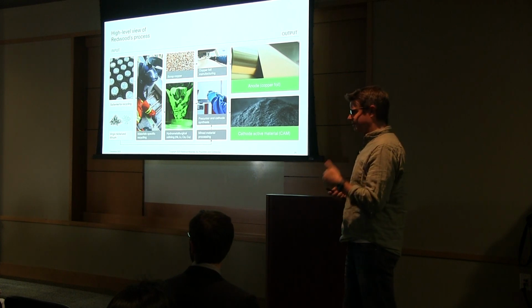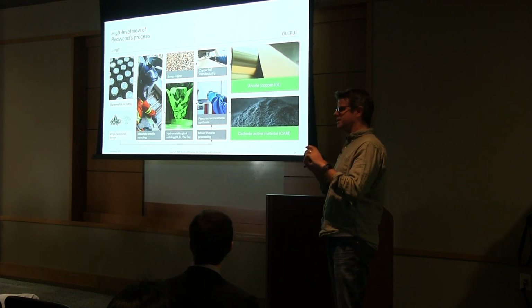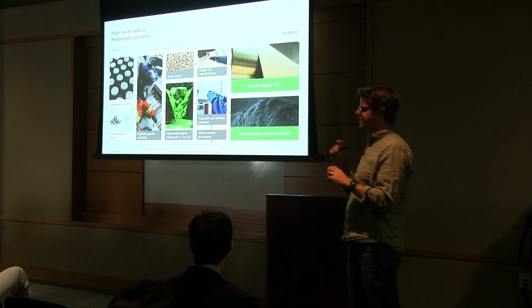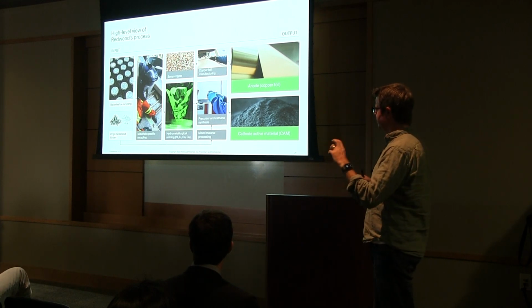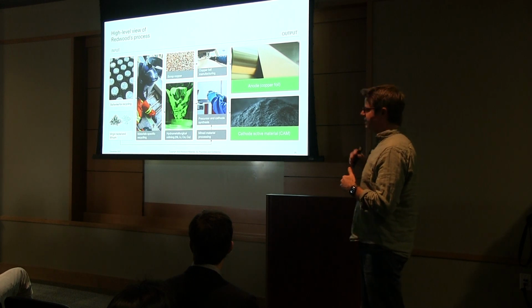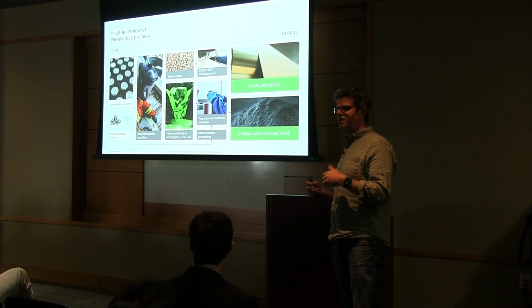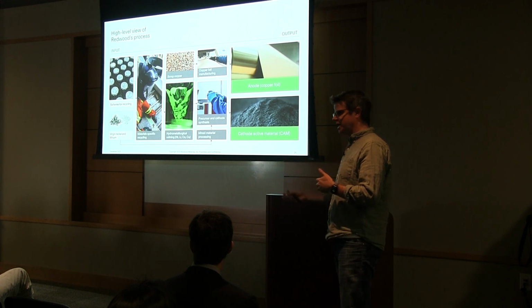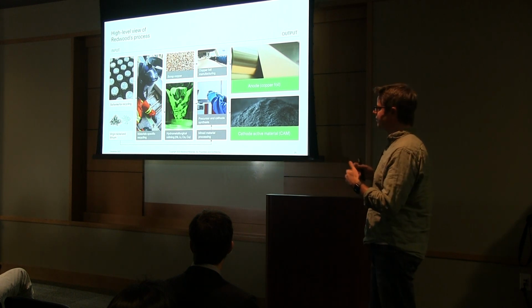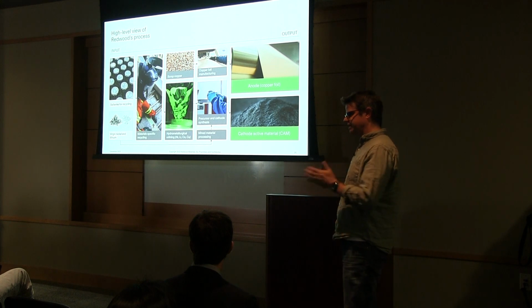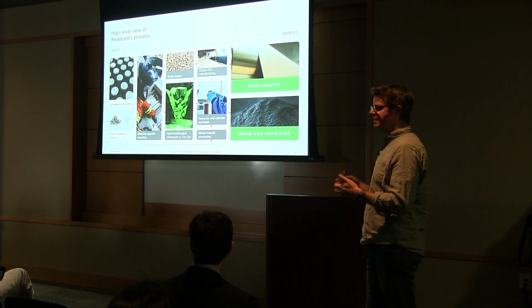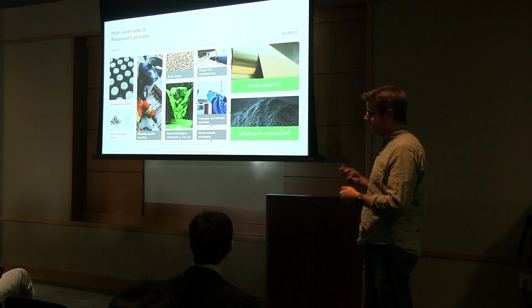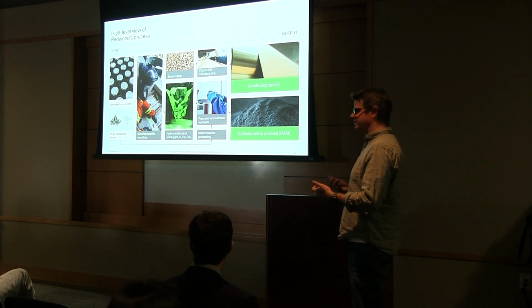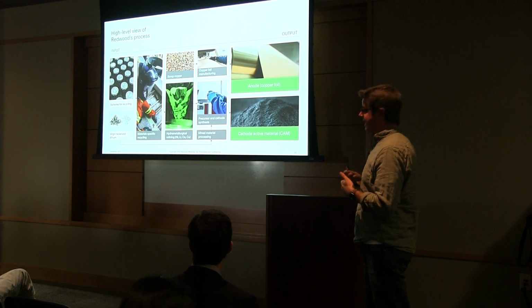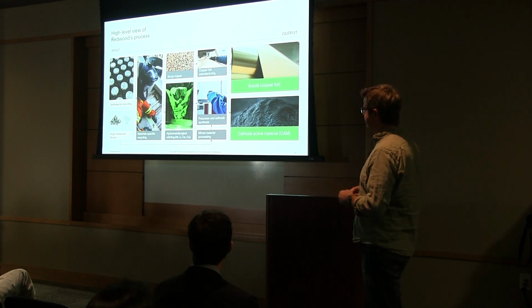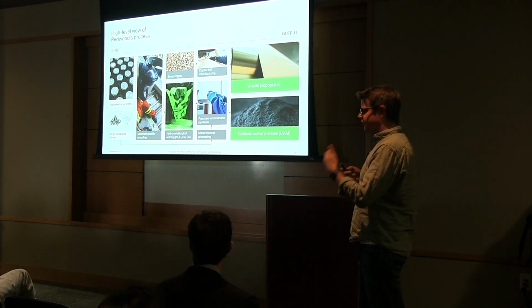For live manufacturing scrap, so these are fully formed cells that contain electrolyte. They have a state of charge. These would be processed through a thermal processing step. Thermal processing for us is how we discharge the batteries at scale. So it's critical that we can discharge these batteries effectively for the downstream processing, but be able to do it at scale as well, because manual dismantling is very cumbersome, it's very time consuming, and it's costly, which affects the overall economics. So this is put through a thermal process.